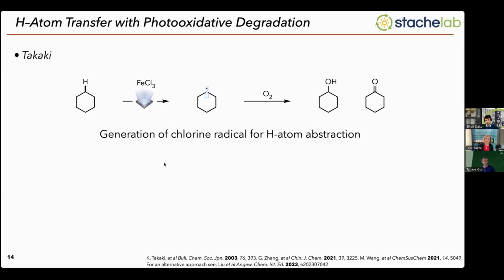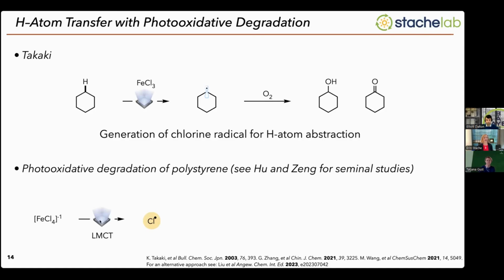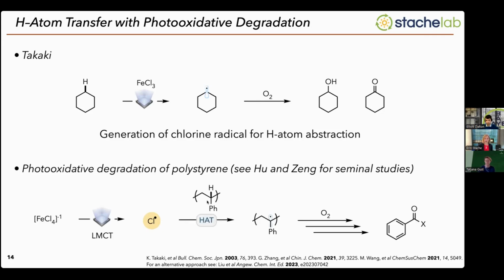And so we were inspired by this work from Takaki, where they used iron trichloride, so a very cheap metal source, to abstract CH bonds from carbon backbones. And then in the presence of oxygen could generate these oxygenated small molecules. And so the way they proposed this worked is that iron trichloride will undergo photoexcitation, undergo a ligand to metal charge transfer, and generate chlorine radical. And as we all learn in sophomore organic, chlorine radical is a great hydrogen atom abstractor. Quickly abstracts even very strong carbon-hydrogen bonds. We proposed that this would abstract CH bonds from the backbone of polystyrene. We could generate free radicals, and then these would react with oxygen and start to break it down into these oxidized aromatic products. And then by getting selectivity over this HAT process, we might be able to divert the product streams.